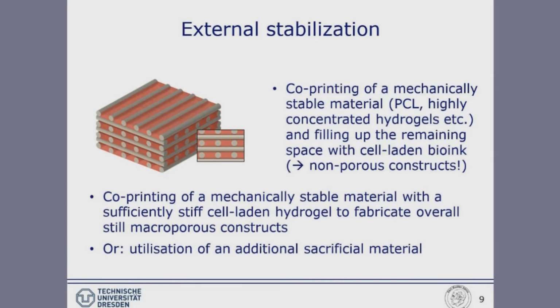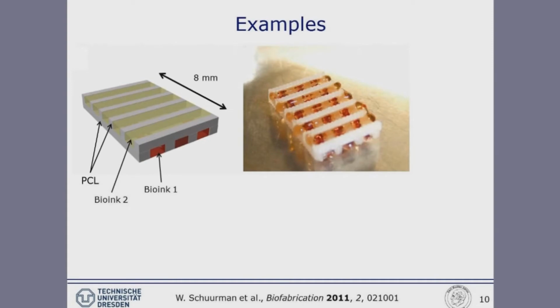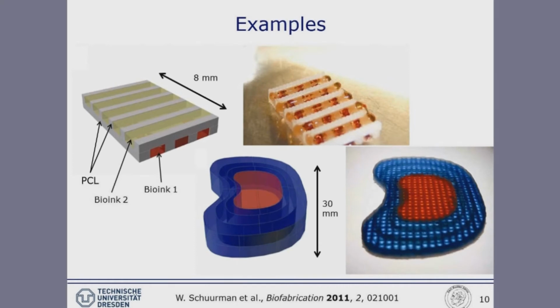The first paper published in this field comes from the group of Joost Malda in Utrecht, the Netherlands, published already in 2011, demonstrating that this combination of PCL, here the white strands, and in this case 2 different cell-laden bioinks is applicable and of course significantly helps to stabilize this type of construct. And they also show already in 2011 that they can print big scaffolds like this very simple model of a human ear with a length of around 3 centimeters.